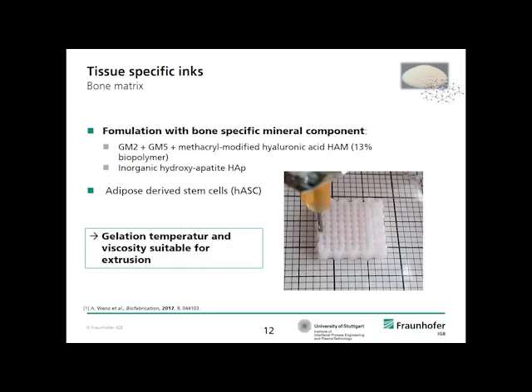the hydroxyapatite powder, to stabilize the function of the cells, which we added, which are stem cells that can, in these inks, differentiate into bone cells, the osteoblasts, and as these cells are in the BioInk 3D environment, which is adjusted to their specific needs, the cells start to produce the bone-specific matrix by themselves. And this is always the idea of these bioprinting approaches, that you start with a material that supports the cells that you use to produce the tissue-specific matrix, to reproduce the tissue by themselves.